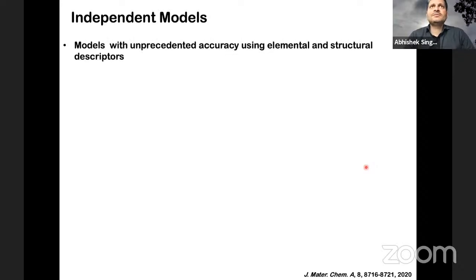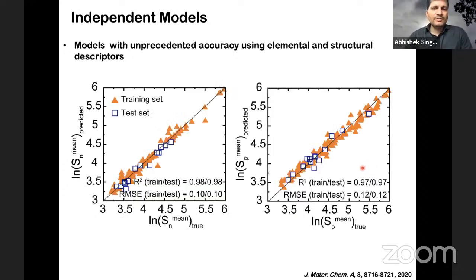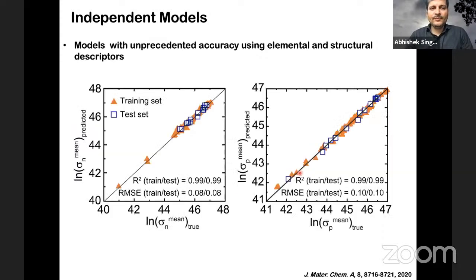However, kappa L, as I told you, is a very expensive property. And for a thermoelectric, we necessarily need to know both transport parameters. Therefore, it would be good if we can somehow correlate our electronic transport to thermal transport, and then we have an idea which one would be a better thermoelectric material. So we first built a model for S, the Seebeck coefficient, for both N and P type semiconductors, and you see that the models were very good. Then we developed a model for sigma, the conductivity. Here again, we got a very good model. You may ask, why are you doing that? Okay, one reason is that we are getting a very good machine learning model.